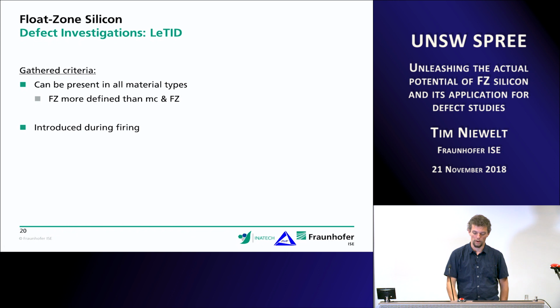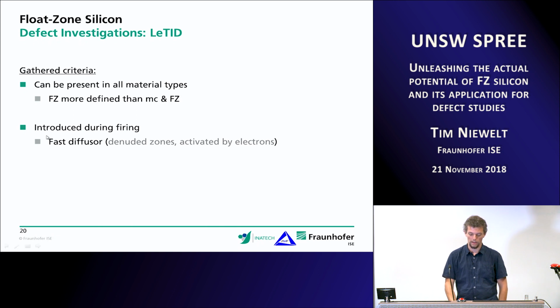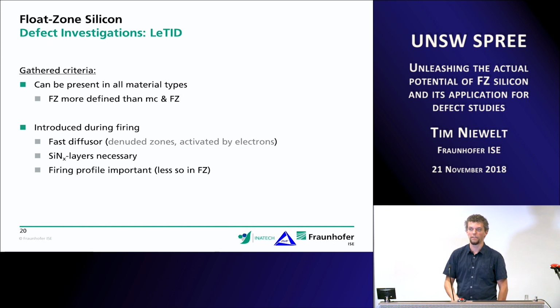We think the one important precursor for the defect is introduced during the firing, only when there is a silicon nitride layer intact. We think that the species needs to be a fast diffuser. I didn't talk about these results in the talk, but we've seen on multicrystalline silicon that there are denuded zones around grain boundaries that indicate that the species needs to diffuse quite fast, and the degradation apparently is directly activated by electrons. As I mentioned, the silicon nitride layer has to be present during firing apparently.